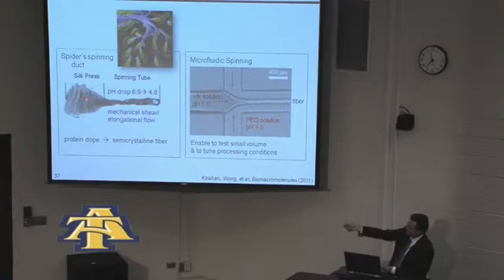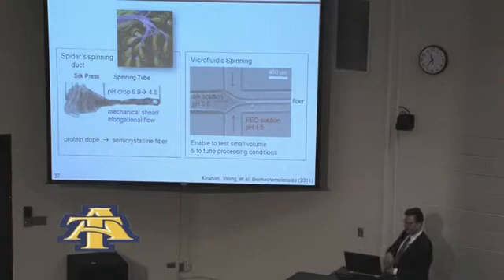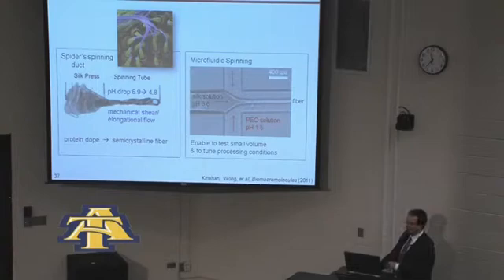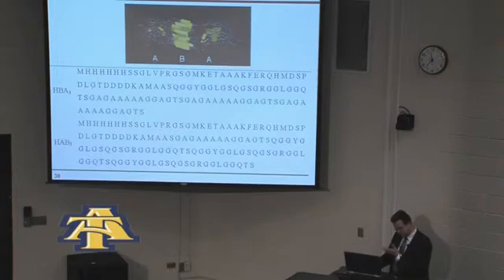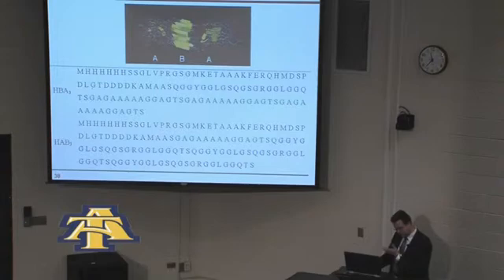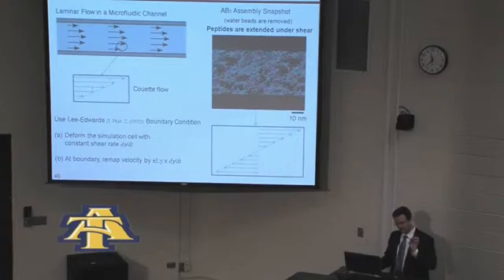We're trying to mimic nature. The spinning duct in a spider, when sliced, has a very complicated three-dimensional geometry with channel flow inside by which the spider produces silk threads. As engineers, we came up with a first-order approximation: a flow channel that thins out, where we inject a solution and change the pH, because we know spiders do this to create threads. We model the molecular structure using big computers and simulate the experiment of flowing proteins through the solution and making fibers.